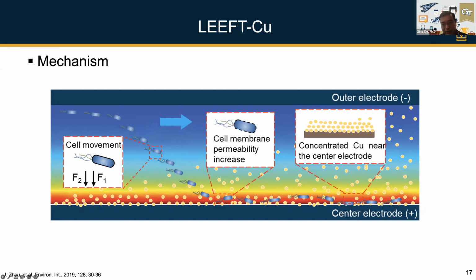At the same time, we know that most of the bacterial cells are actually negatively charged. So when they flow through the system, they will get closer and closer to the center electrode. In the system, we still try to maintain the condition that the cells are not collected by the center electrode. We do see some collection, but still more than 80%, 90% of the cells flow through the electrode. So most of them are not accumulated inside the system, close to the center electrode. But the point here is that the cells will move towards the center electrode, where you have the stronger electric field and also higher copper concentration. So this effect plays very synergistically to enhance the inactivation performance of the system. Okay, so that's how this system works with the LEEFT combined with copper.